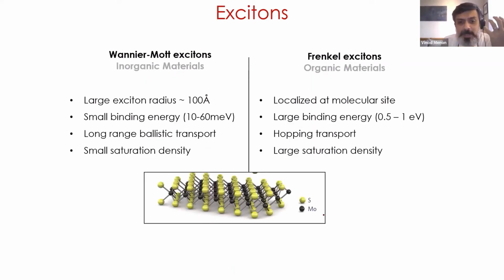So the bottom line is that the excitons in these 2D transition metal dichalcogenides really are Wannier-like, but with properties that sometimes start to resemble what happens in the case of Frenkel excitons. So again, you're getting a best of both worlds scenario here, where you're getting these large binding energies and so on, but you still have Wannier-like excitons.